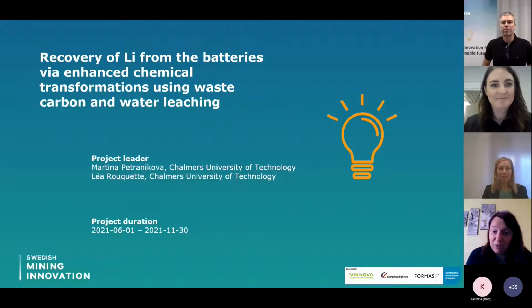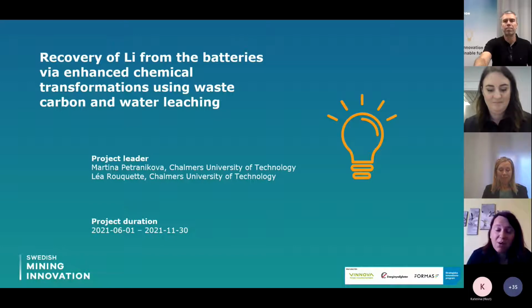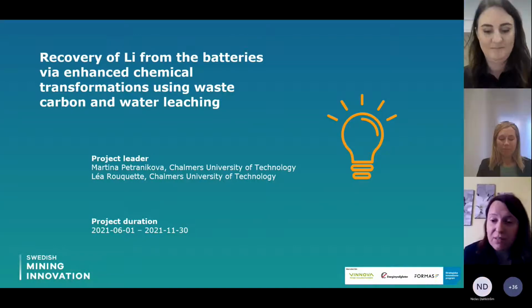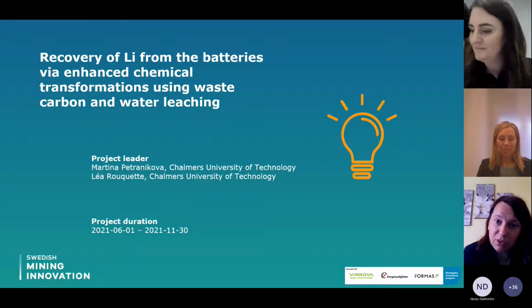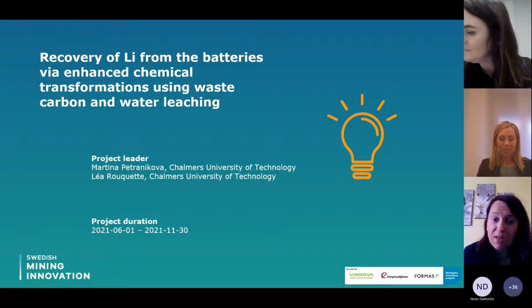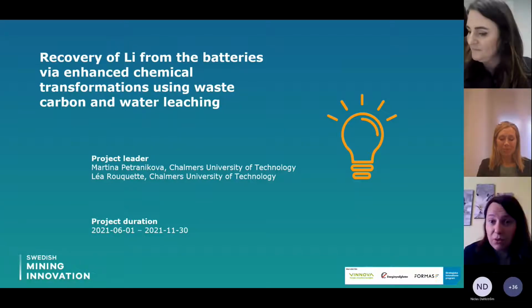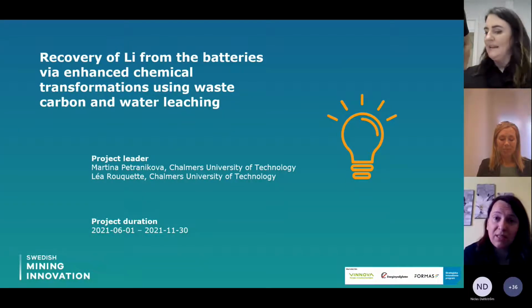So why recover lithium? Because the demand of lithium is increasing rapidly, and for the European Union, lithium is a critical raw material. So we really have limited sources of lithium in the European Union. What we can recover it from are the batteries. But nowadays the batteries are recycled using either pyrometallurgy or hydrometallurgy. In pyrometallurgy, the lithium is rarely recovered, but in hydrometallurgy it is. However, in some steps, lithium is lost. So then it is recovered in the end as the product.